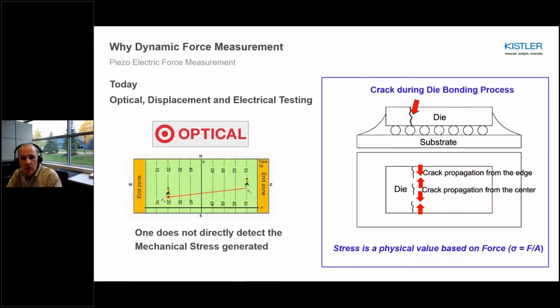Here we have an example on the right side of the screen. A known good die is attached to a known good substrate. While each component appeared to be within good tolerances prior to the bonding process, during the assembly phase, an actual crack developed as shown within the die. Force deviations occurring during the assembly process can lead to quality issues. For the next 30 or so minutes, I will elaborate more on this, but let us first examine what's under the hood of a dynamic force sensor.